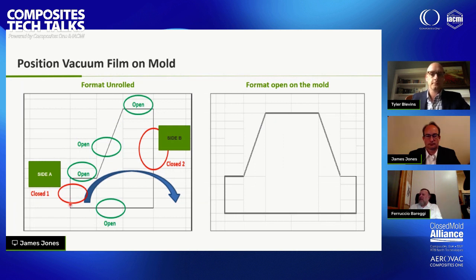Once that is cut, you only need to unfold the format onto the mold and directly seal the bag on the flanges, on the technical flanges. You don't need to cut off any excess of film anymore. So you reduce your waste of material, and you avoid a somehow risky operation, handling scissors or sharp knives around the bagging film that is sensitive to cuts.